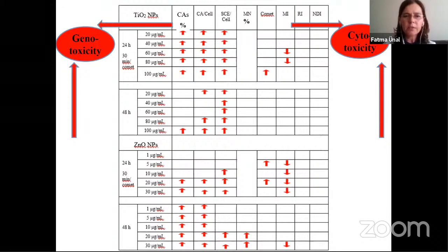In this table, we can see the concentrations of both nanoparticles that increase the frequency of chromosome aberrations, chromosome aberration per cell, sister chromatid exchange per cell, and the frequency of micronucleus and damages in DNA. All these red arrows show that these concentrations increased these aberrations significantly compared to negative control. These results show that these nanoparticles induced genotoxic effect in human lymphocytes. On the other hand, these nanoparticles decreased the frequency of mitotic index compared to negative control. These results show that these nanoparticles have cytotoxic effect in human lymphocytes.